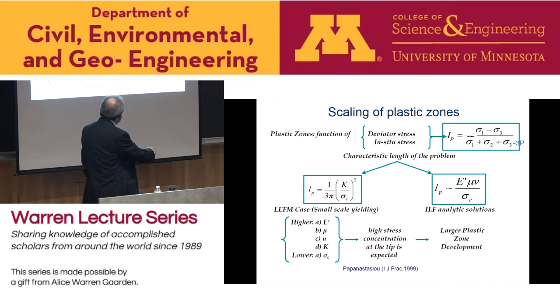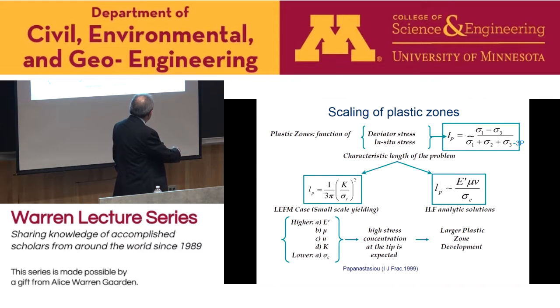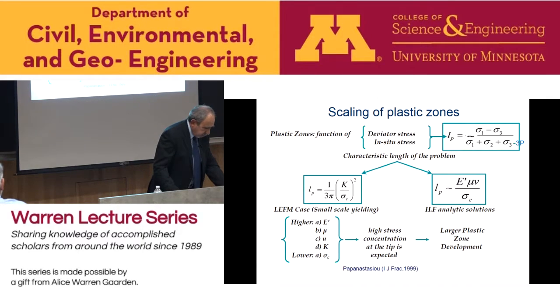And there is another characteristic length which was produced by a solution we worked on in Schlumberger Cambridge Research when Emmanuel was there. And then it was investigated further, which basically says that this plastic zone will depend also on the Young's modulus, the plane strain Young's modulus, the pumping parameters, viscosity and flow rates, and the compressive strength of the rock.